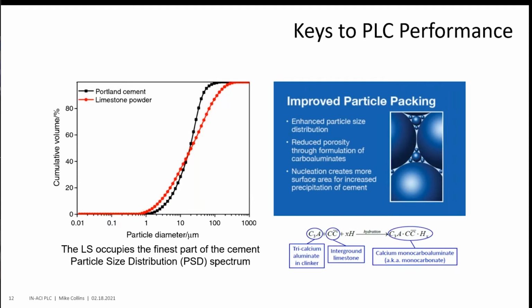We're taking the cement particle size distribution, which would be the black line, and we're blending in the fine limestone powder. And so what that does, again, is kind of fill in some of those gaps in the actual particle size distribution of the cement. That actually drives a lot of the good stuff that comes out of the performance issues that we see with Portland Limestone Cement. And so some things that start to happen is we see an enhanced particle size distribution. So in other words, that cement typically would make a denser concrete. That leads to reduced porosity.